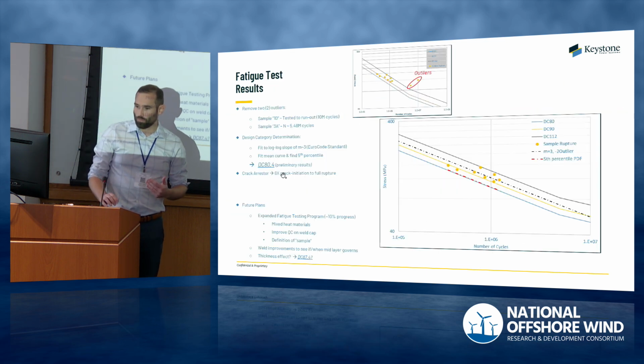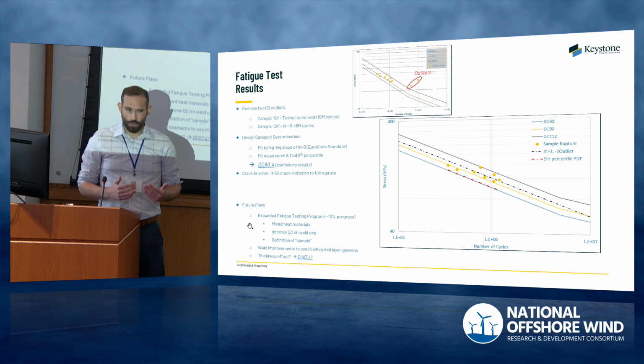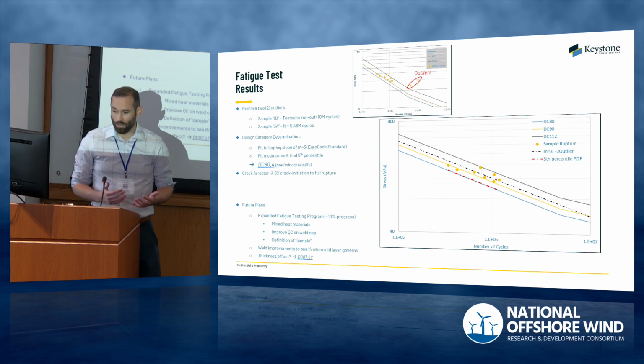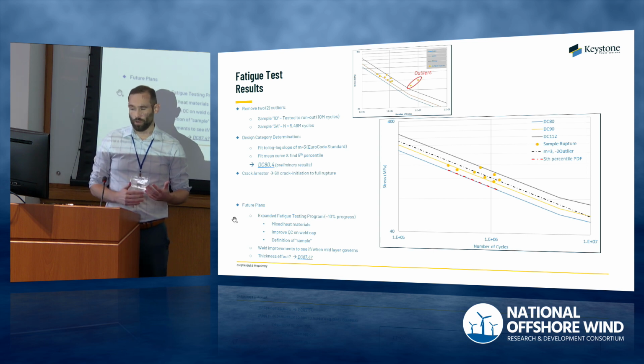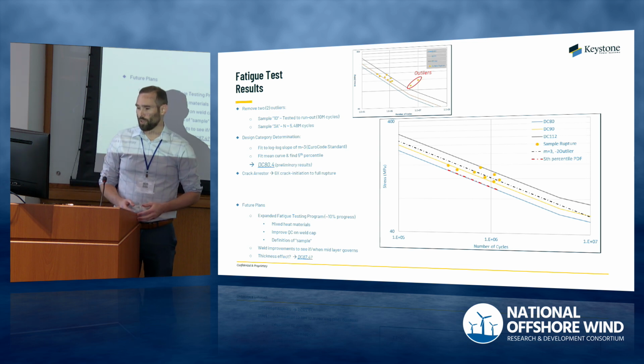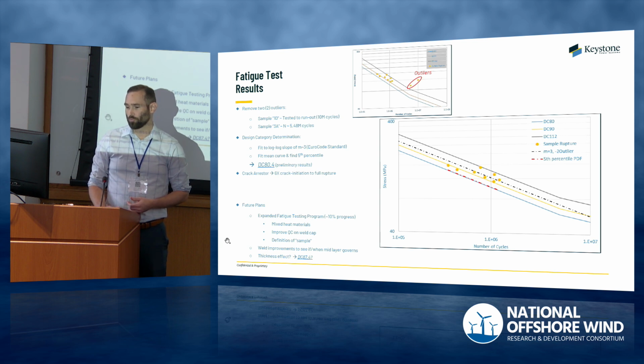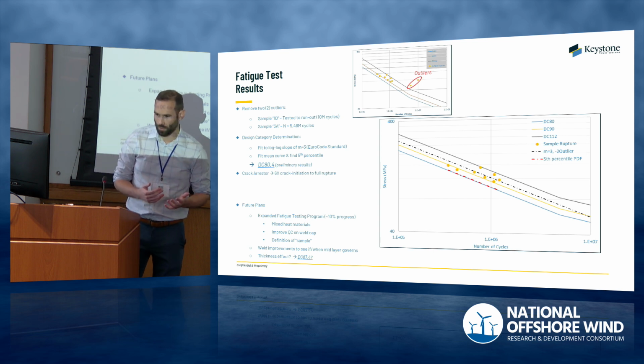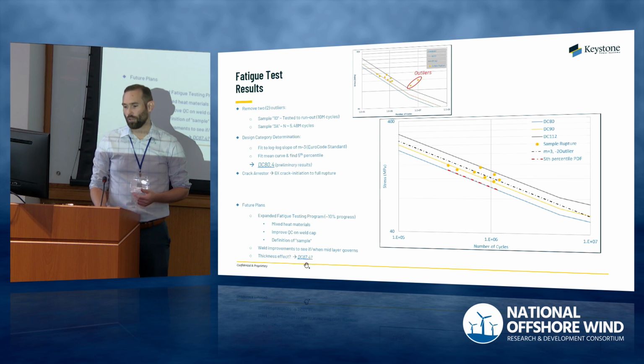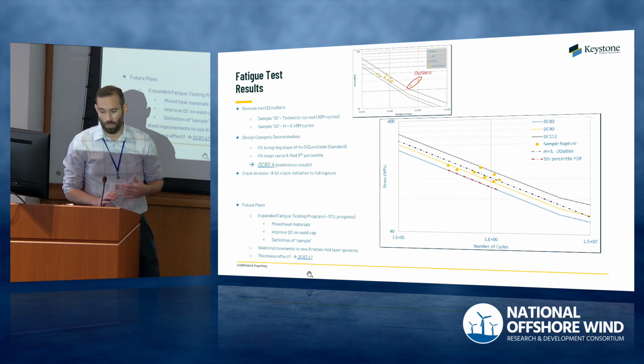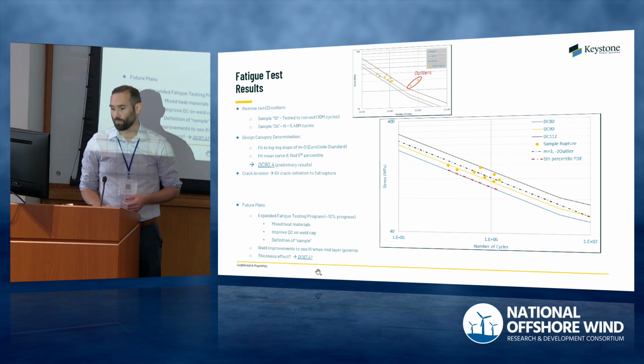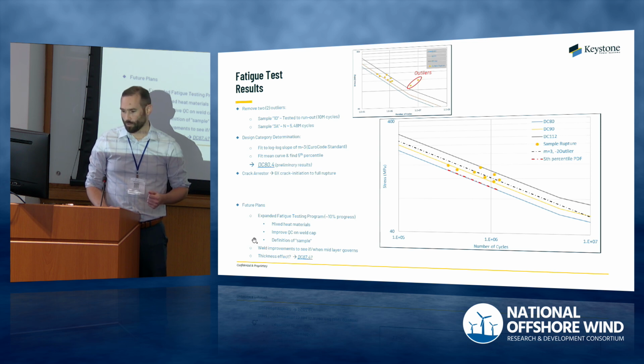And this represents a very small test sample, actually. This is maybe about 10% of a full fatigue test program, so there's more testing to be done. This was for a 1.5 inch thick sample in total. One thing that's not totally clear is whether the thickness limitations of fatigue details would still apply to this. If so, if you took into account the thickness effect, this would maybe be a DC80 design category. That's sort of to be determined.